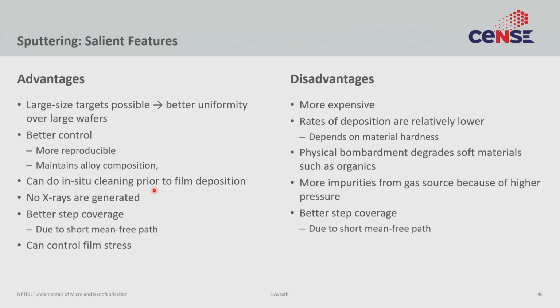There are no X-rays generated because there are no electron beams, and you do get better step coverage, partly because the mean free paths are much shorter, which means the arrival angle of the flux is much wider, so it actually tends to deposit in all directions. Like it's less directional than evaporation. And finally, you can control film stress because you have this additional parameter, which is the energy of the incoming atoms. And by changing the voltage, changing the energy of that incoming atom, you can actually change the stress.